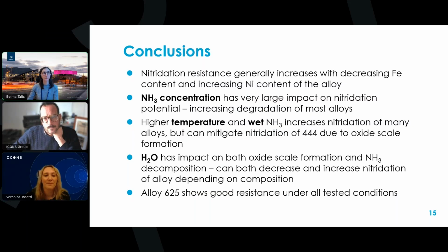Yeah, so the content of steam, when we added it intentionally, was 2 volume% in all cases. In the dry conditions, we did not have any intentional additions of steam. The duration of all of the tests was 200 hours in total.